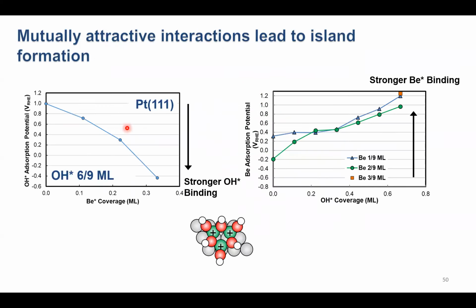I'll just briefly show, we have lots of DFT data. I'm not going to show all of it here. We've also used DFT to examine these interactions. We can look at the adsorption of hydroxide on this surface. So we calculate the hydroxide adsorption potential at one particular high hydroxide coverage as a function of beryllium coverage on the surface. And we see a strong promoting effect. So beryllium strongly promotes OH adsorption on the surface.